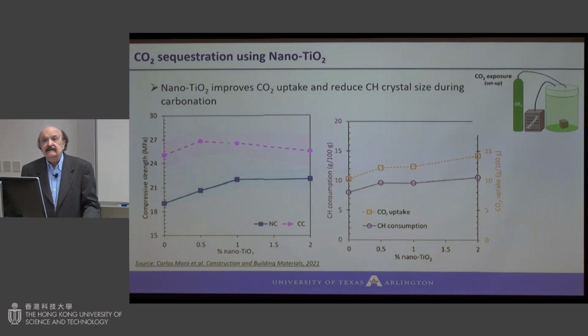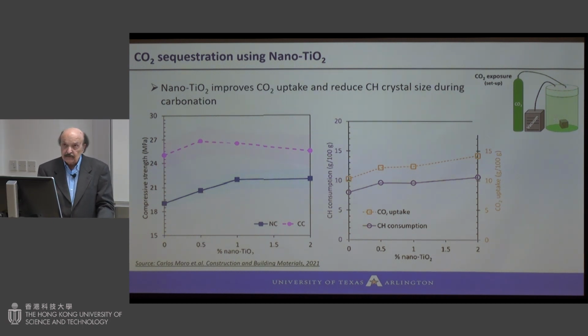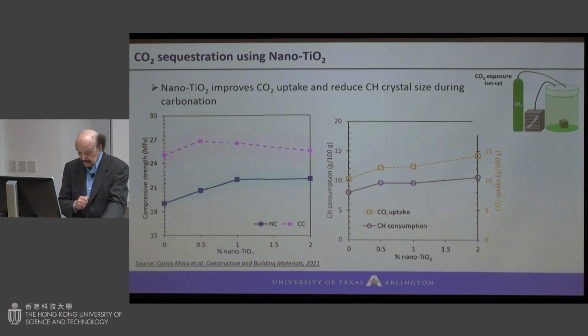So I thought that was a good idea, and it turns out that we have been working, as many of you know, with graphene-based materials. Carbon nanotube quite a bit, graphene oxide and graphene. And I had a postdoc, Chin Wang. She's at Beijing Civil Engineering University. And she found that when you add graphene oxide, calcium hydroxide crystal is reduced. And as a result, many of the properties improve, when you have a very small amount, and I will talk about it a little bit later on.